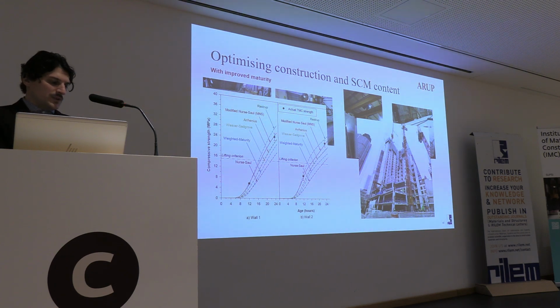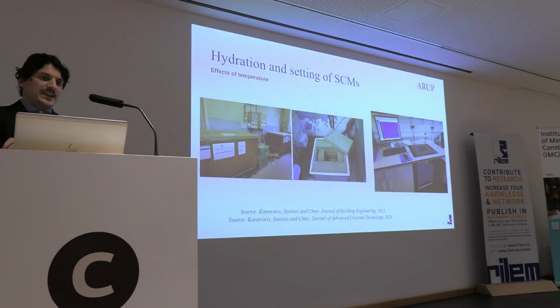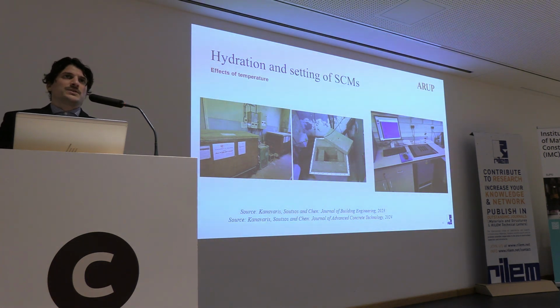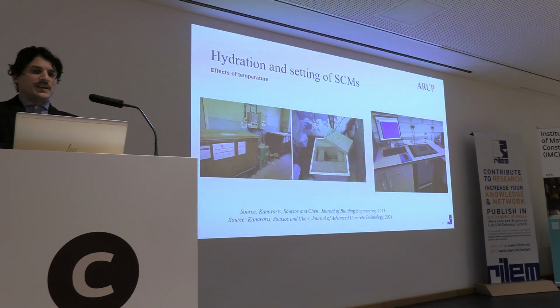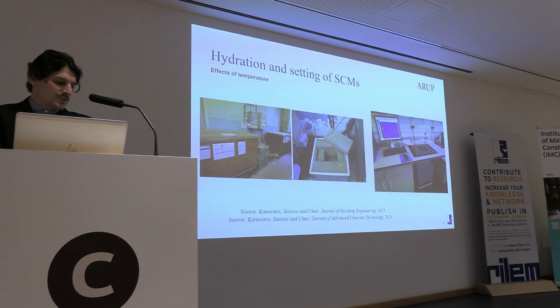We were able to use 50% of slag in the summer and 25% in the winter, while it was traditionally zero, actually, straight Portland cement in these cases. But as part of these studies, we of course had to investigate hydration and setting of these supplementary cementitious materials, and developed custom-made adiabatic calorimeters that you're seeing on the left-hand side, and also isothermal calorimeter studies.